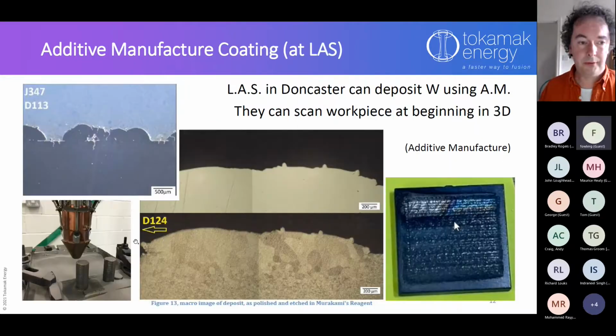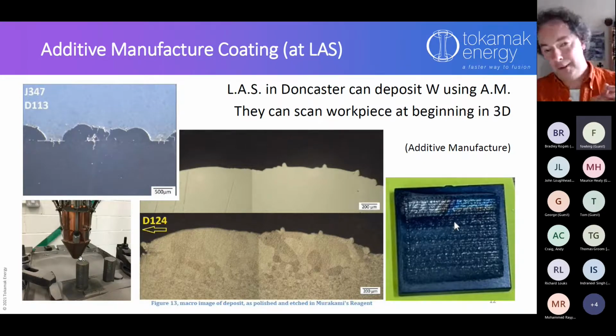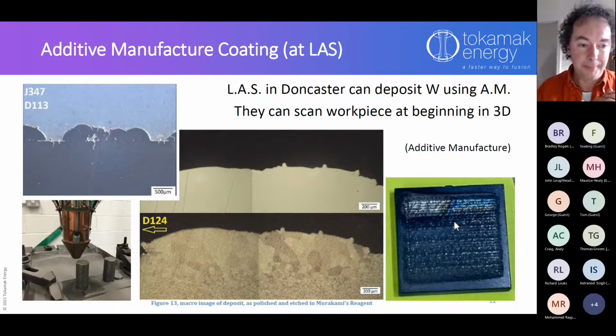I thought I'd show those samples. This is the deposition head they have, and it's all rather exciting. There's basically a laser here, and these are powder feeders. So tungsten powder is blown down here. The laser is fired at exactly the right place and exactly the right time to melt the tungsten just right on the surface, and you can basically do 3D printing like this.